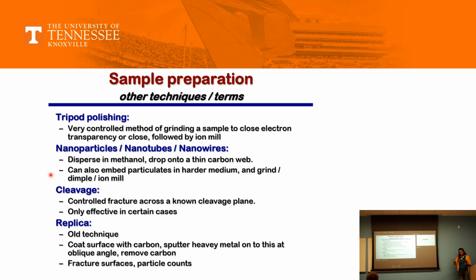And there they used to have these particles dispersed in a liquid. And we used to take a grid and literally fish those particles onto the grid. We used to have a carbon grid, and that carbon grid is simply your TEM grid with a wire mesh inside. You would take the tweezers in the lab, take your carbon grid, and immerse it in a sample which has nanoparticles. As you immerse the grid into the solution, your grid will take some of the nanoparticles. These nanoparticles are actually trapped in this grid. And that's what you take inside your microscope and start analyzing.